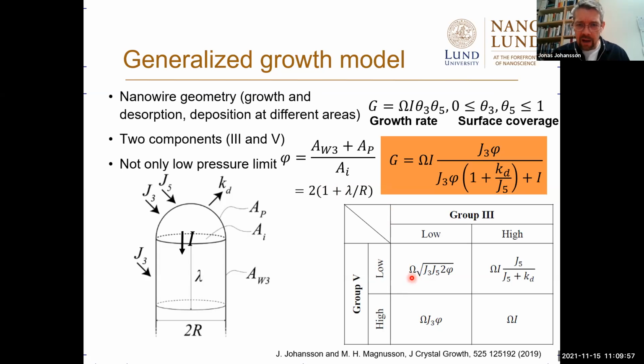For both low group 5 and group 3, this expression, we cannot derive that from this equation here. We have to take one step backwards. And then we have a square root dependence of both group 3 and group 5. And I don't think this has been observed very much. Perhaps it has been observed in 1 or 2 experiments, because I remember a paper, CB growth, was it Lucia Sorba and Sibirev did some modeling, maybe. Quite interesting.